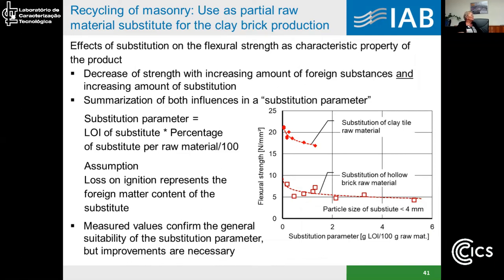We found a decrease of the strength with increasing amount of foreign substances and increasing amount of substitution. Now I've tried to summarize both influences in a substitution parameter. And that is the definition of this parameter: it is the loss of ignition of the substitute and the percentage of the substitution, multiplied. The assumption behind this definition is that the loss of ignition represents in any way the foreign matter content of